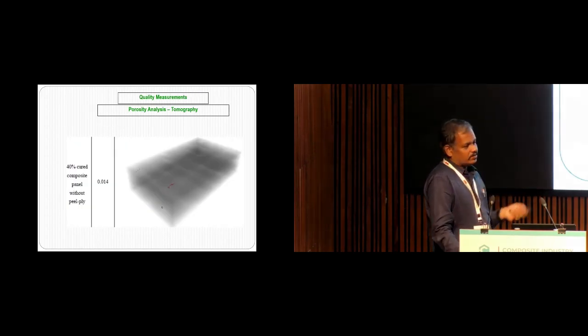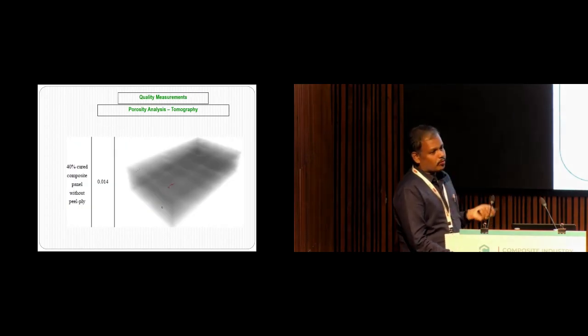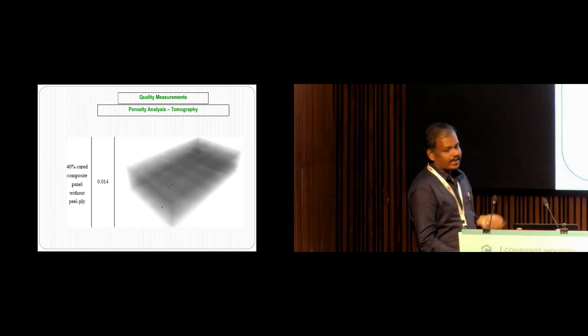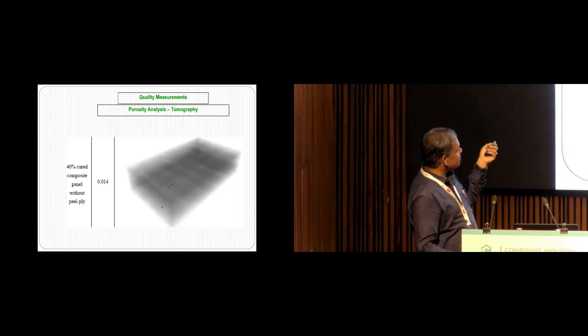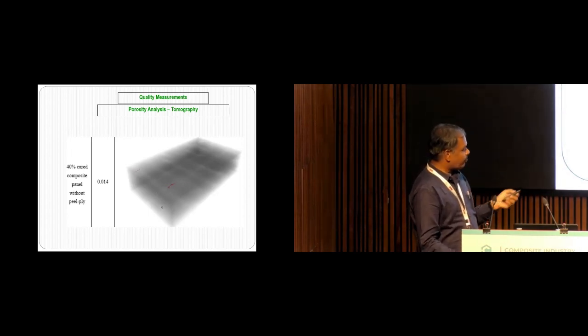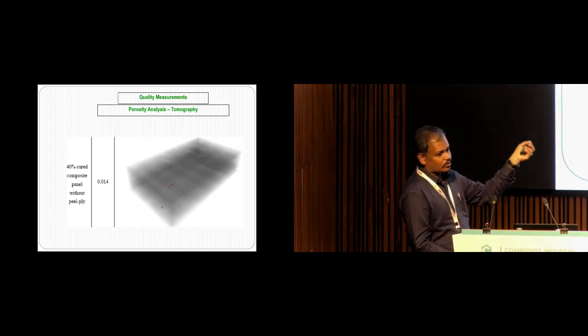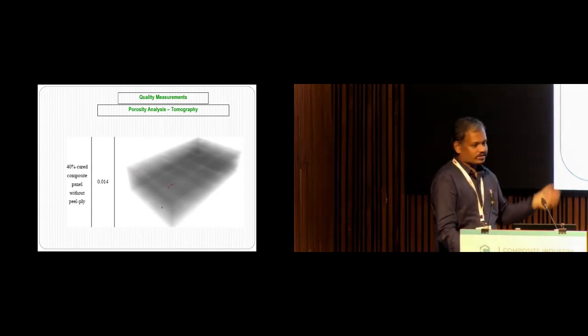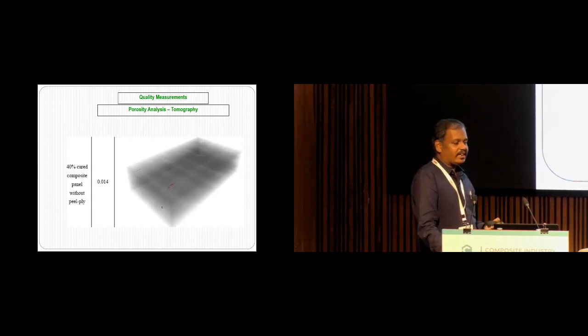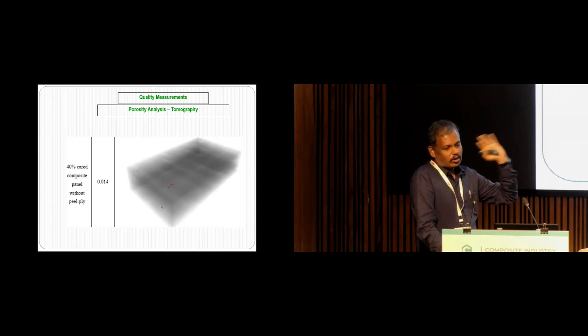We have done X-ray tomography also. As we said, the pore volume is to be less than 0.1%. Here it is 0.014%, which is very much appreciable. This is for a 40% cured composite panel without peel ply. You can see that the red points are the pores. So what we are concluding here is that, irrespective of going for autoclave molding,